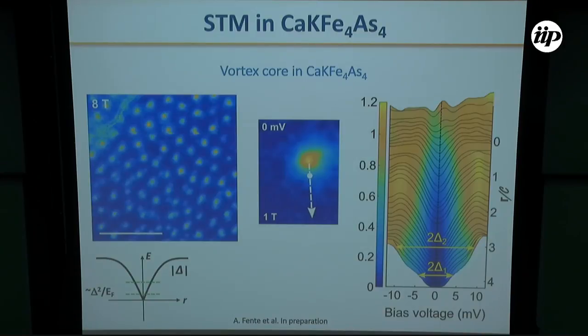One possible explanation for this is that, as I mentioned before, ARPES data have seen that this gamma band, this alpha band, disappears very close to the Fermi energy, and this can produce an electron-hole asymmetry that can influence the shape of the core state in this material.